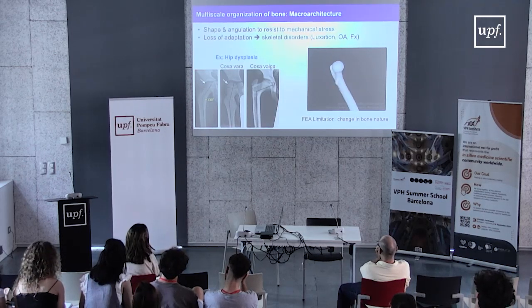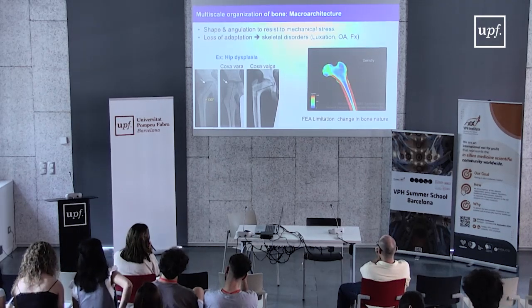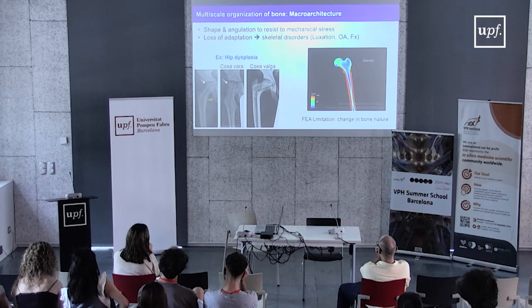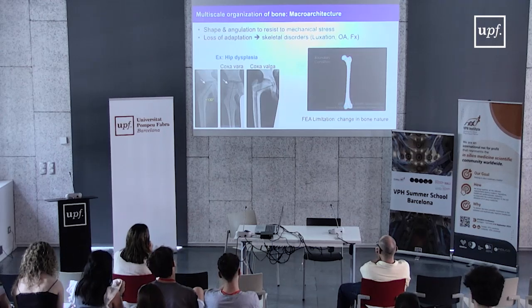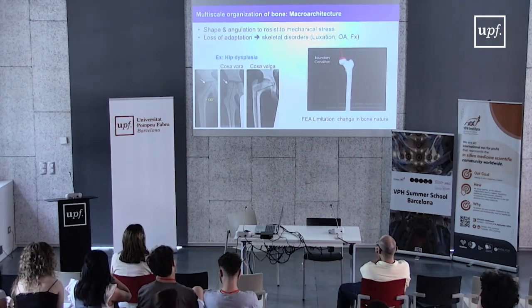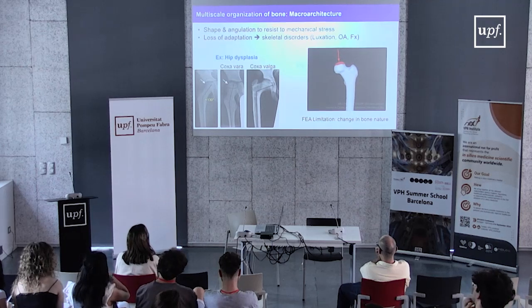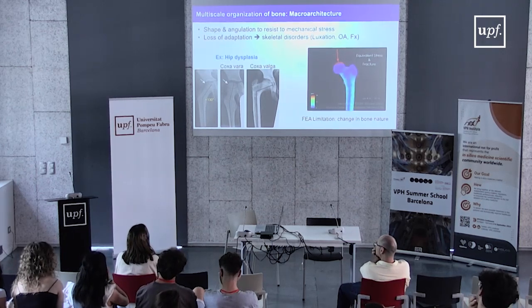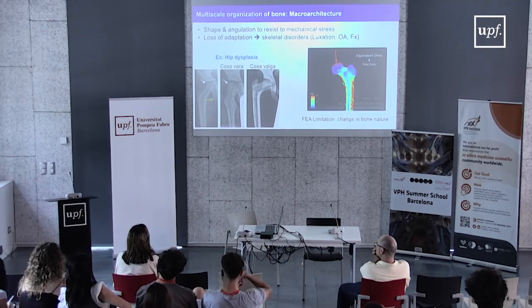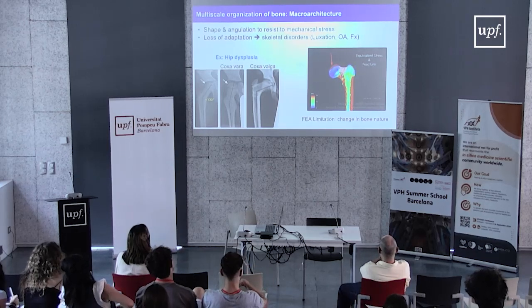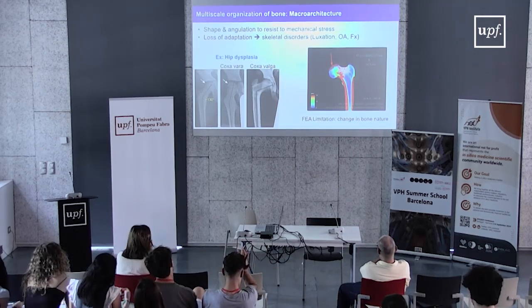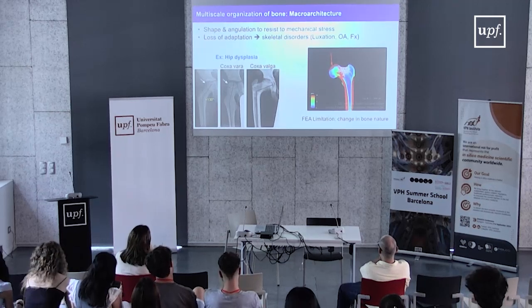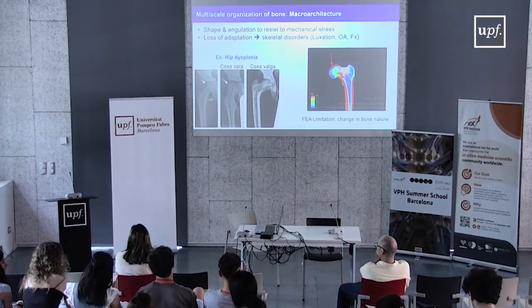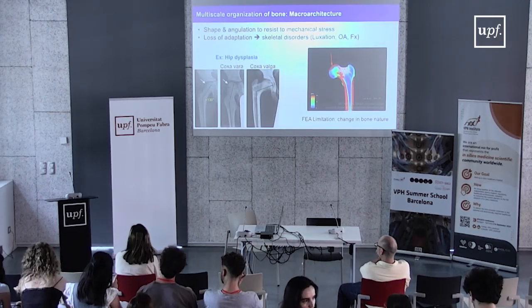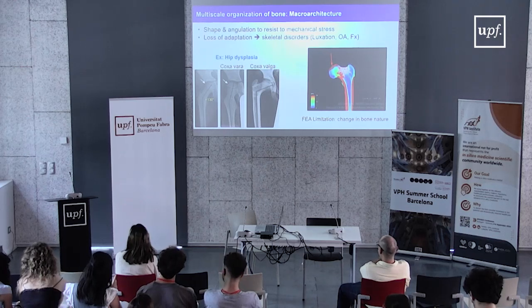If we make a finite element analysis on this shape of the bone, and especially when we transform our normal bone into a coxa valga, we will see that it's easier to break the bone, or at least to estimate the force which is required to break the bone. Here again, the limitation of this FEA method is that we don't take into account the quality of the bone matrix and the texture of the bone matrix.